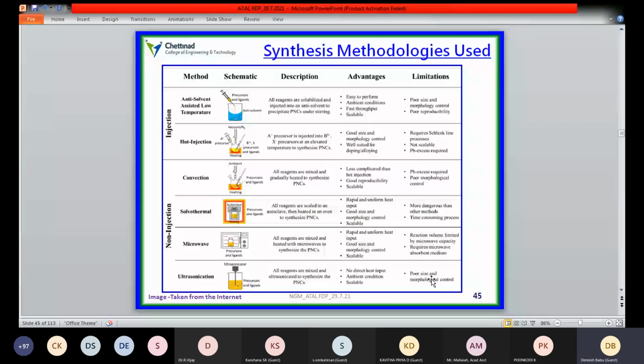For the preparation of these perovskite systems, people use two different methodologies. One is called injection and the other is called non-injection based systems. In the injection based systems, people use the anti-solvent assisted method and the hot injection method. With these two injection based methods, we can get particular size-constrained materials, with good size and morphology control. These two methods are also suitable for doping and alloying. If you want to dope lead with tin, germanium, antimony, or bismuth, we can easily dope with them, and we can also play with their structure.